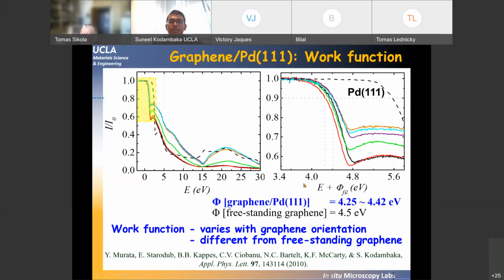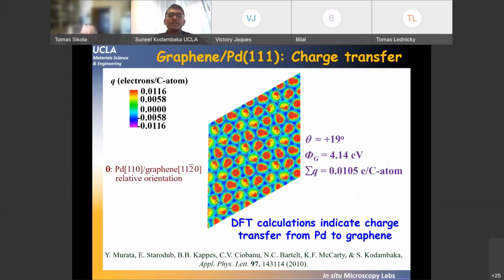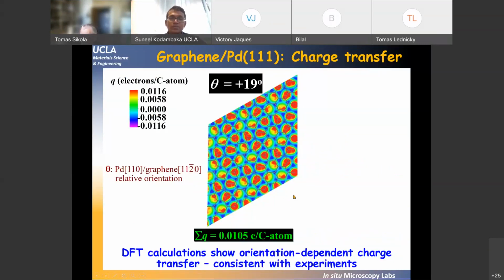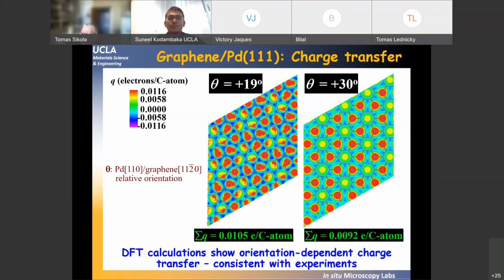And what you see here is that the work functions of different domains of graphene can differ by up to 170 millielectron volts. So each of the domains with different orientation on palladium has a different work function, and that's because from density functional theory calculations, you see that there is a charge transfer from palladium to graphene. And the amount of charge transfer depends on the orientation. One can imagine that if you have two layers, depending on how each layer is rotated with respect to the other layer, the amount of interaction between carbon and palladium can change. Okay?